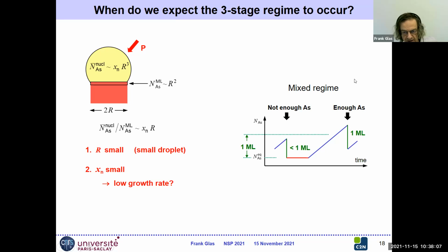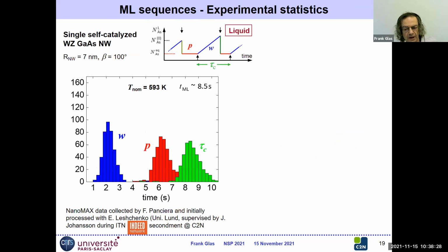And of course, we can imagine mixed regimes where, because of the conditions, for some monolayers we wouldn't have enough arsenic to grow a full monolayer. And sometimes we would nucleate when we have enough arsenic, so we would have this mixed regime. So I very much would like my colleagues to observe it in Nanomax, but this has not been observed up to now. So now I suppose I have only 2 minutes to speak about statistics.